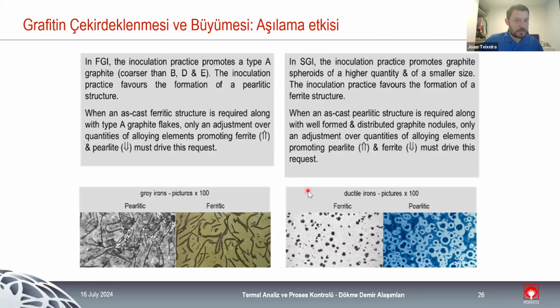So inoculation is there to promote that type of graphite. And normally for gray cast iron, inoculation favors a pearlitic structure. So it favors a pearlitic matrix. And this is not the case for nodular. To have a pearlitic matrix with nodular cast iron, normally we need to add either copper or tin to the melt. And the objective is to have a lot of different spots for the germination of the graphite nodule. We are going to also add magnesium to promote the transformation from gray to nodular. And inoculation is there to give a lot of solidification points for the nodules to grow.